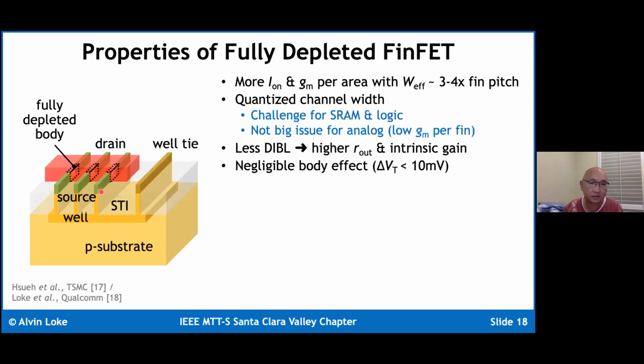Now, there is a caveat, because this technology with HighK metal gate, replacement metal gate technology, has caused a marked reduction in the allowable maximum channel length. And so although for a short channel length you get better intrinsic gain, you're losing out in not having very long channel lengths anymore, okay? The body effect in this technology is very negligible, which is no surprise. You can pretty much check out all your body biasing techniques, because your threshold voltage will shift no more than 5 to 10 millivolts across a body bias of supply.